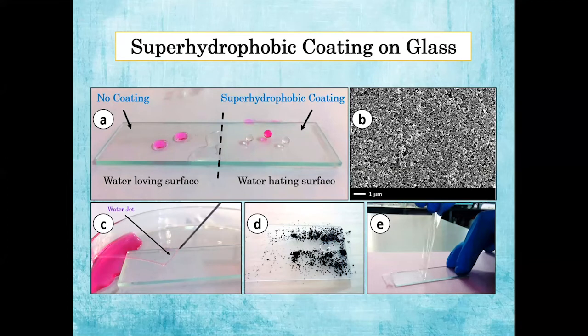You can see this surface morphology using the scanning electron microscope images. You can see the silicon nanoparticles are trapped in the PMMA network, and you can see the compact and porous morphology. We also studied the durability test in C and E images. In C we use the water jet impact test, and in E we use the adhesive tape test, and we could observe that the coatings are moderately stable.